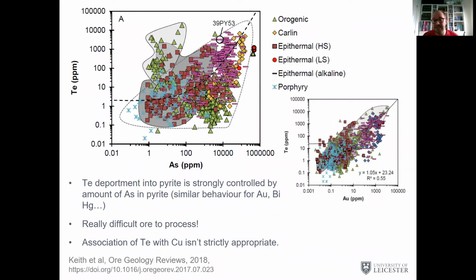The problem is that pyrite is actually a really difficult mineral to process, not least because one of the main mechanisms by which pyrite becomes enriched in trace metals is by a lattice deformation effect, where arsenic substitutes into the pyrite lattice. So to recover tellurium, gold, bismuth, other metals that we're interested in from pyrite, we're also going to be extracting arsenic, which has obvious toxic effects in the environment. Also, other metals would accompany those critical metals that we're interested in, things like mercury. So we risk, by processing that pyrite, generating more problems or more hazardous waste that we would then be obliged to process further, whereas in the pyrite, it's perhaps more dilute and more manageable.